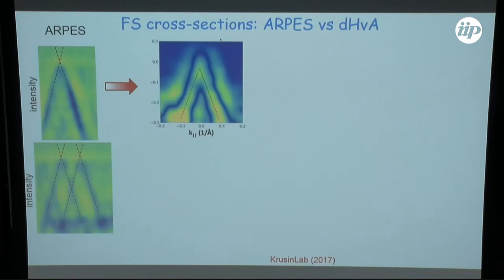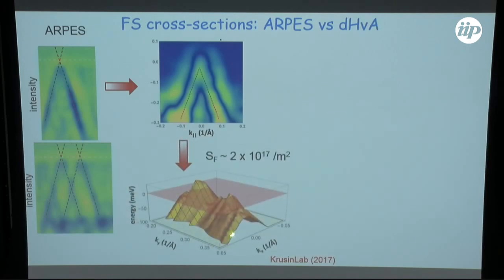And the analysis that he had done basically looked at the map of the subsurface states. And one thing that was actually quite remarkable is that the subsurface states were also linear. They kind of look Dirac-ish, but obviously they're not surface states, right? But they're linear, so depending on where your chemical Fermi level is, the particle is still very low mass. And if you map it carefully, and there is a lot of variation in the system, obviously. So this is Ky, this is Kx, this is the energy or intensity. And this transparent red or pink plane is where the Fermi level is. What we can get is actually the cross-section, the Fermi cross-section, from which we can estimate the carrier density.